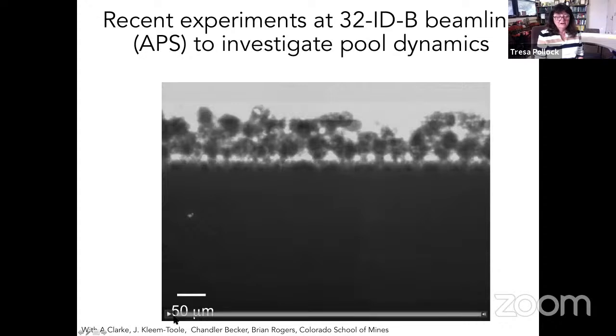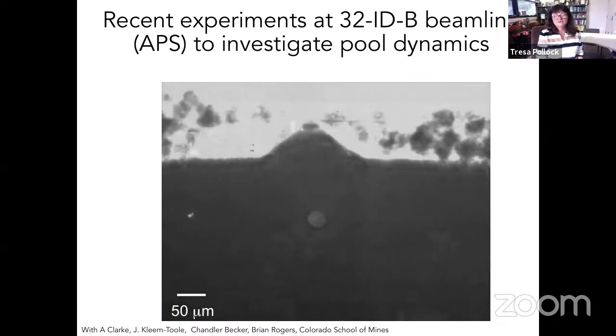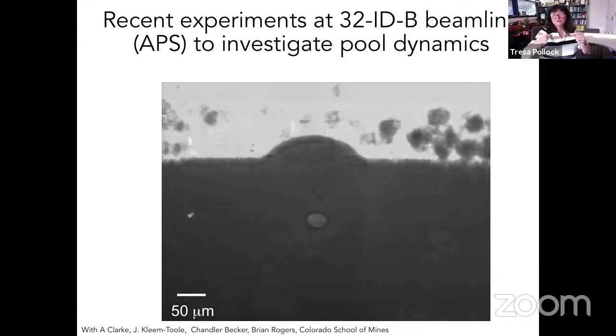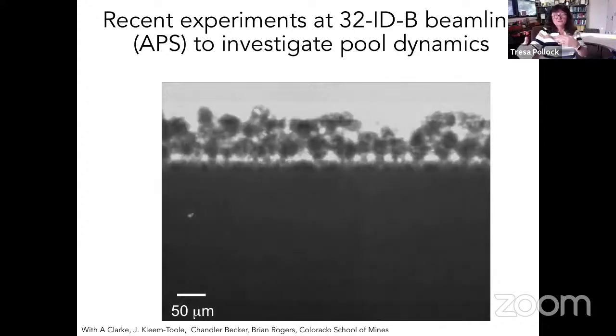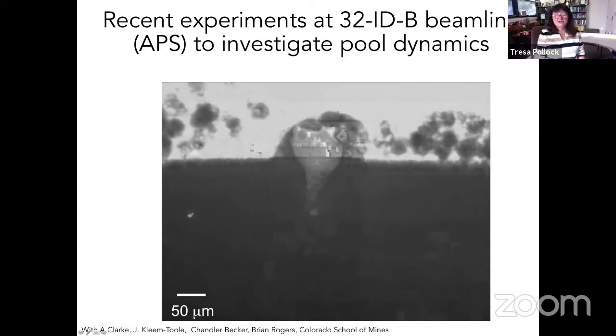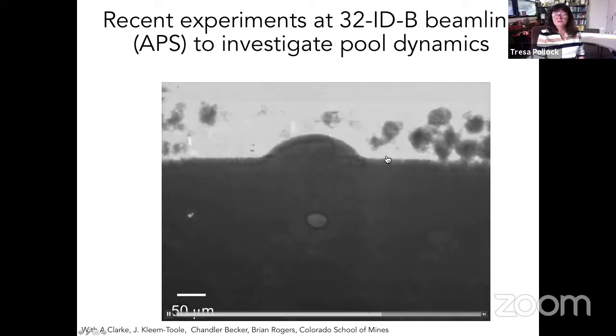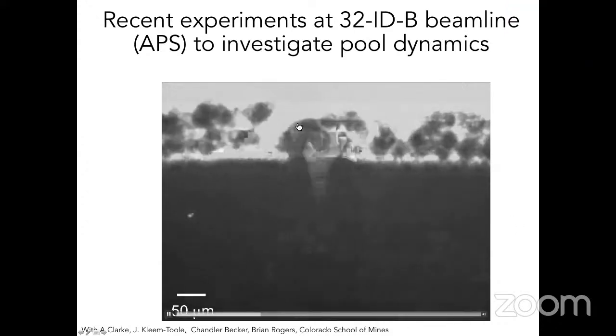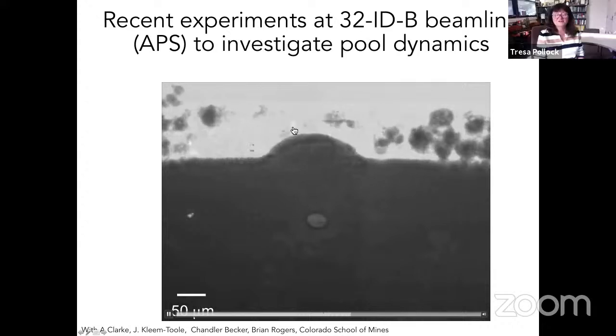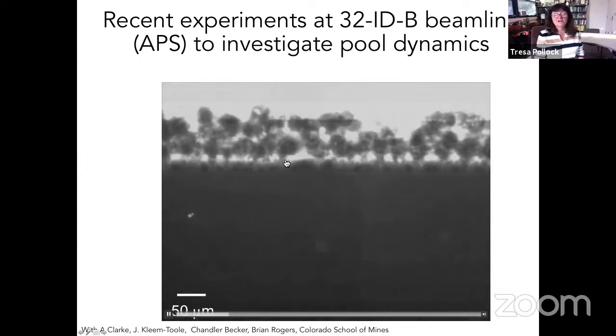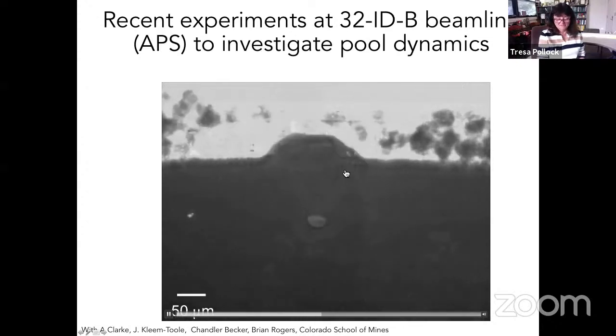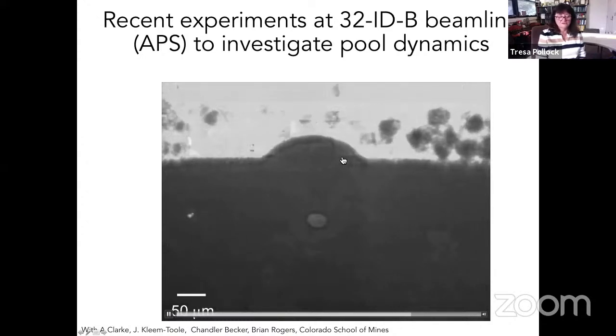Now I show here an experiment conducted in collaboration with Amy Clarke at the Colorado School of Mines. And this is at the Advanced Photon Source, where one can take a small sample and, using X-ray imaging, scan a laser beam across the surface. And so you can see individual powder particles here. And in looking at this movie, it's quite obvious that this is a very complicated process to control from the point of view of where physically all the powders are and what goes on in the liquid, and understanding how to control that over very large volumes.